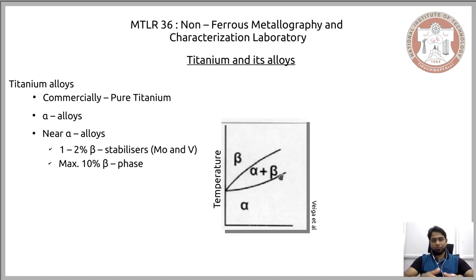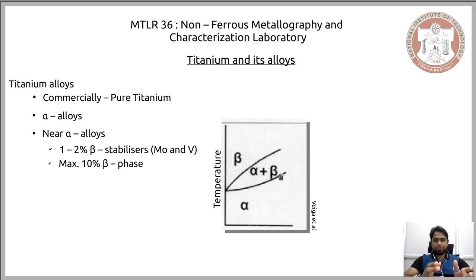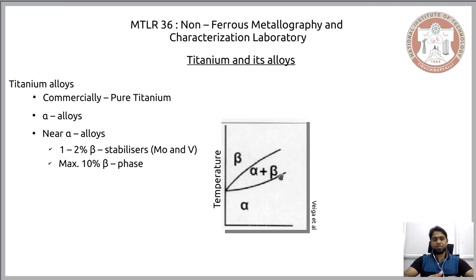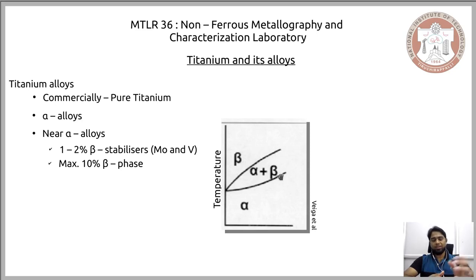The next category is near alpha alloys. In addition to alpha stabilizers, one to two percent of beta stabilizers — largely molybdenum and vanadium — are added as alloying elements. The inclusion of these beta stabilizers facilitates a certain amount of beta phase at room temperature. The maximum beta phase achieved by this inclusion is 10 percent, so near alpha alloys can have up to 10 percent beta phase.